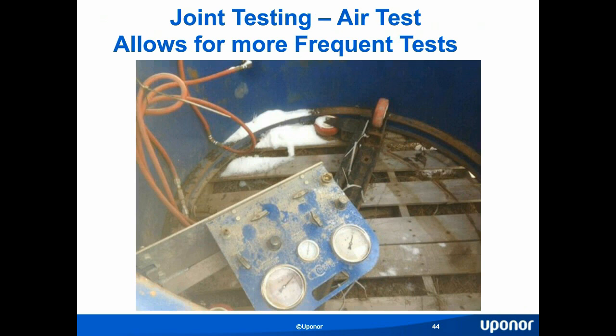Another test that we can do, and this is becoming more and more popular, is an air test. You really can't see it from this photo, but I'll describe it to you. It's 2 bladders, and in the middle, there is a gap. The 2 bladders fill up with air on both sides of the joint, and that's creating your seal. And then this other gap, this third gap, is just at the joint itself, and that's where we actually inject the air at a certain pressure.